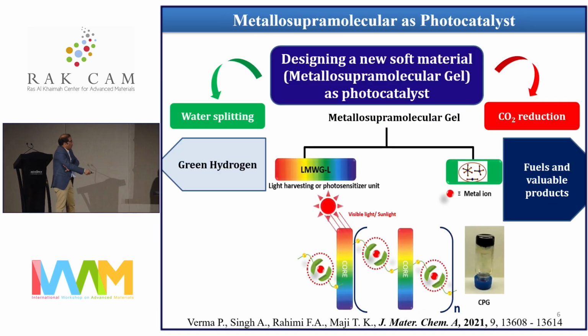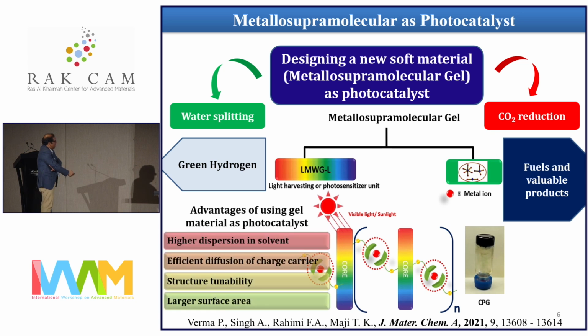In our approach, if you have the supramolecular catalysis, you want to target green hydrogen production. So what it can do: you have the core, you can use the light harvesting moiety, and you have the covalently attached metal ion, which can act as the co-catalyst, or you can further introduce another co-catalyst which can act as the catalyst for either green hydrogen production or CO2 reduction. So you have this advantage.